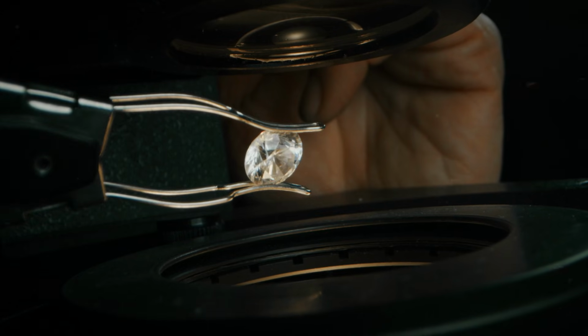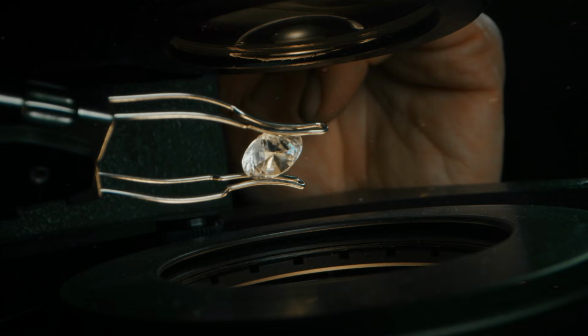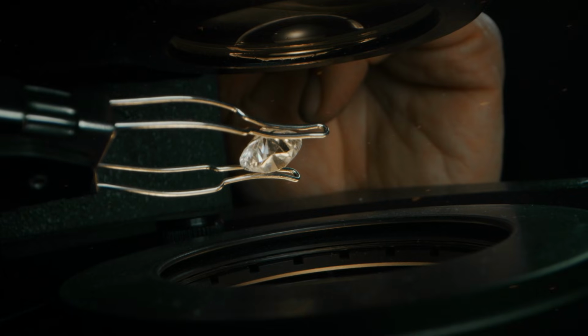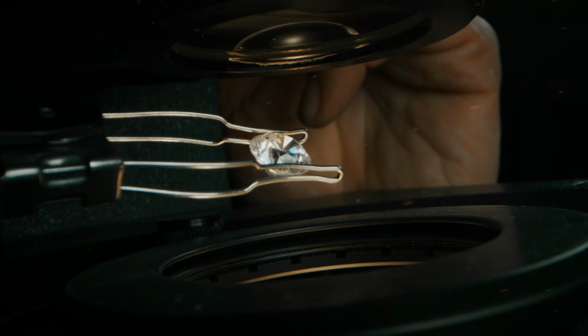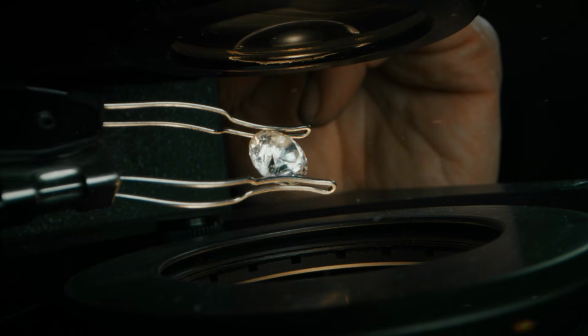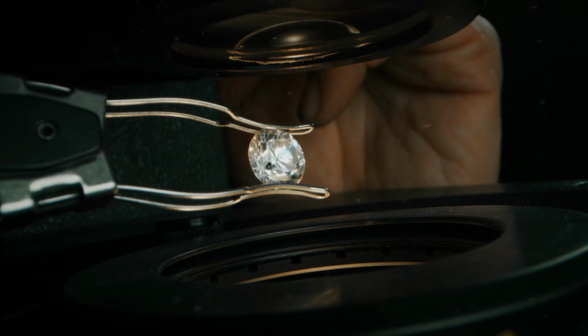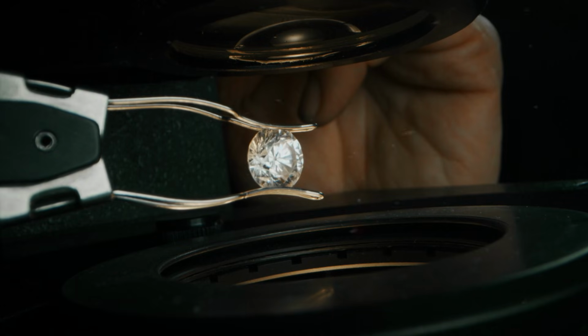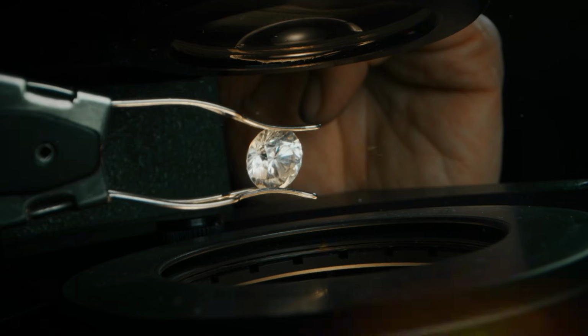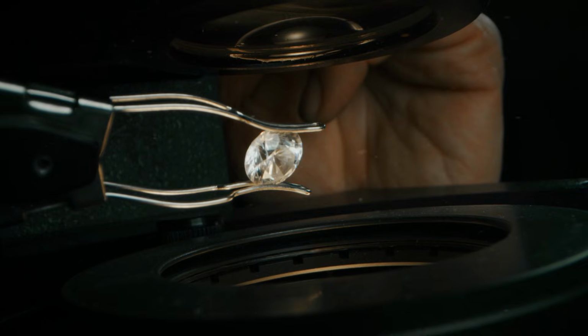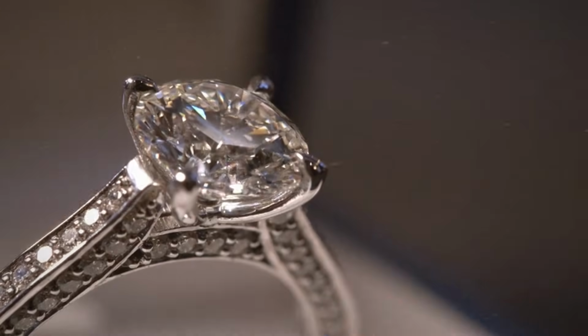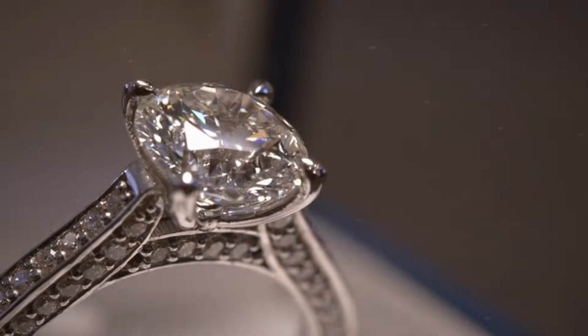Proper technique is essential. The probe must make firm contact with a flat, clean facet, usually on the table of the stone. Oils, dirt, or curved surfaces can cause false negatives. It's also important that the stone be stabilized. Loose settings or small melee diamonds may shift under the probe, disrupting the reading.